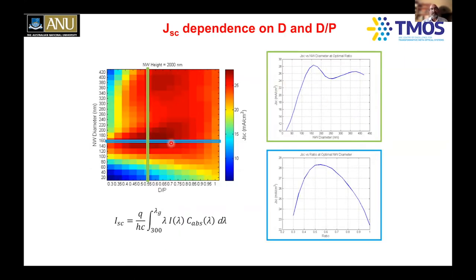That's where you see a large amount of current, here is the scale. You can see the red means you're creating a larger amount of current here, and blue means you're creating very low current here, for example. And then also the diameter to pitch ratio, where pitch is the distance between the nanowires, should be around 0.5 or 0.6, where you get the maximum amount of current being generated. That's what you want to make use of. And again, this plot tells you essentially the same thing.